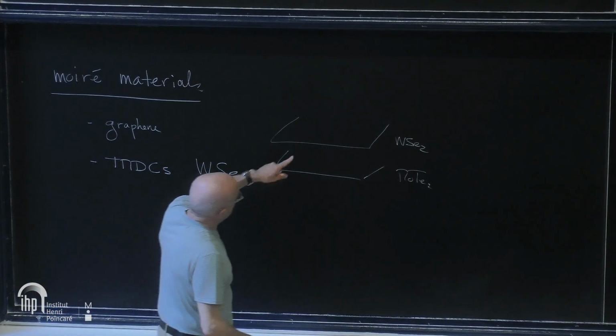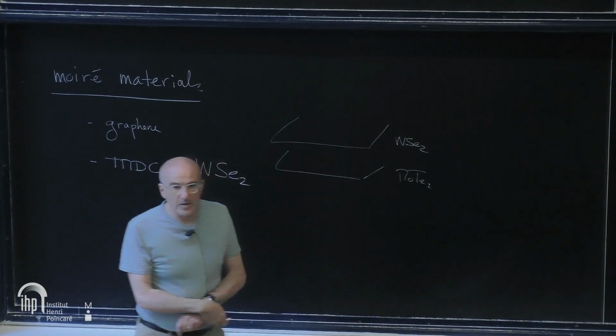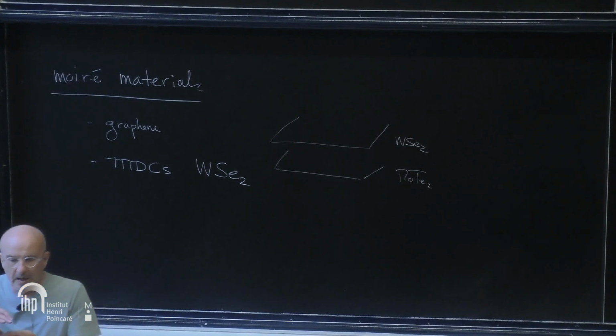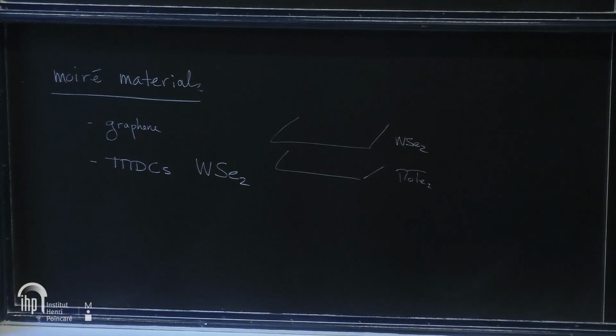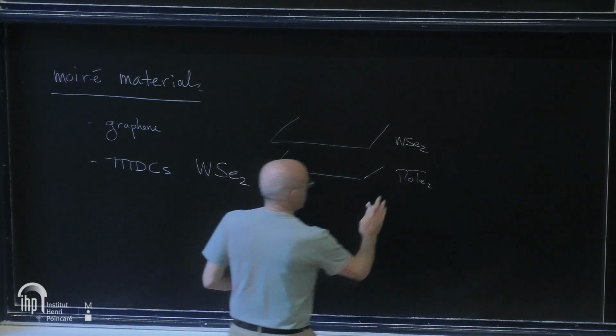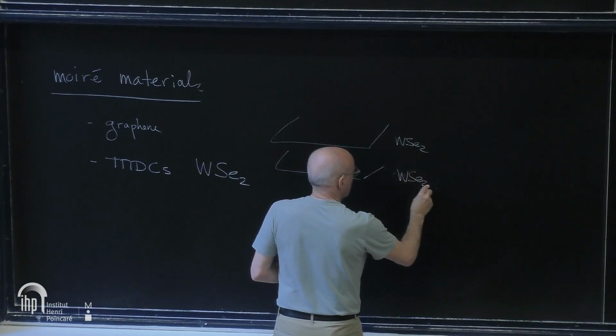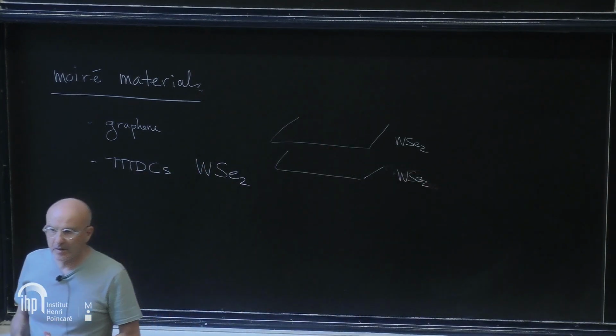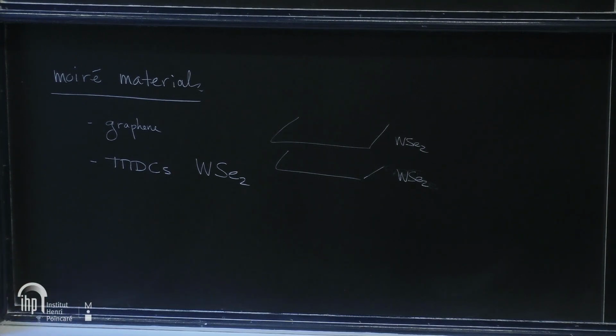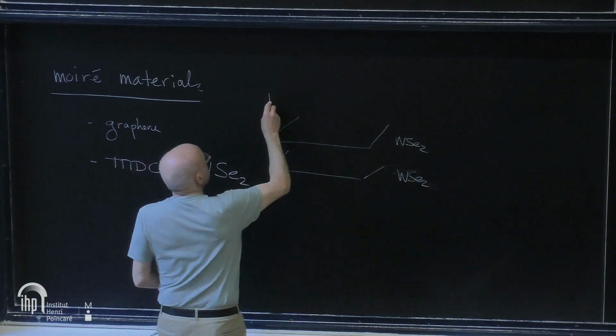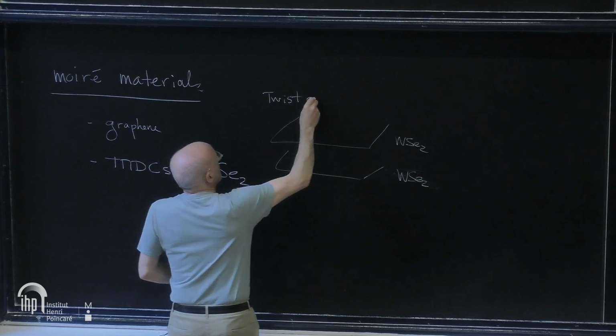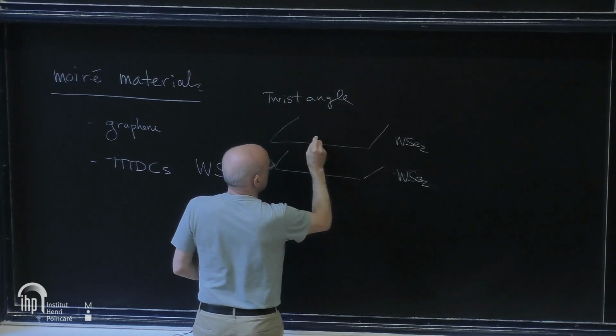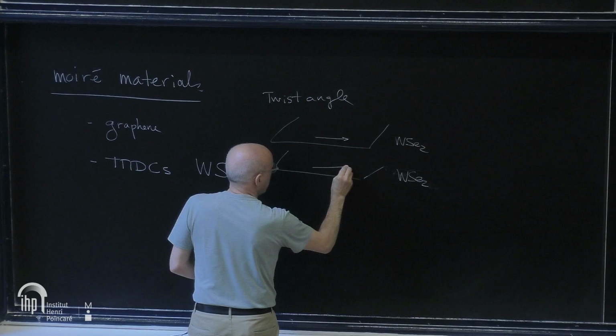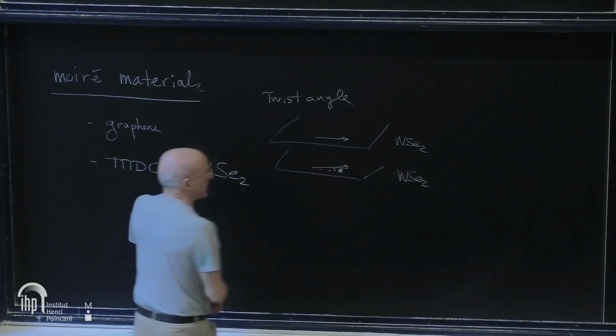And both of these materials are 2D crystals, but they have different lattice spacing, or you could also take the same material, and what physicists and chemists can do is actually rotate slightly one plane with respect to one another with a controlled angle. So this is called the twist angle, in which the main axis of this plane and this plane are rotated by a certain angle theta.